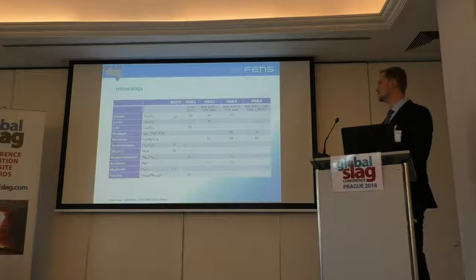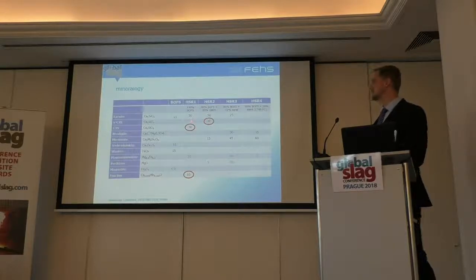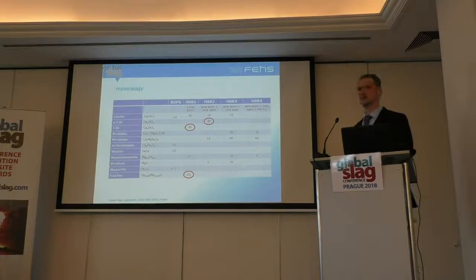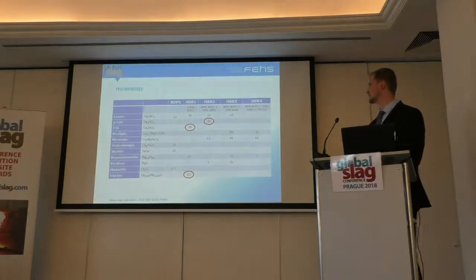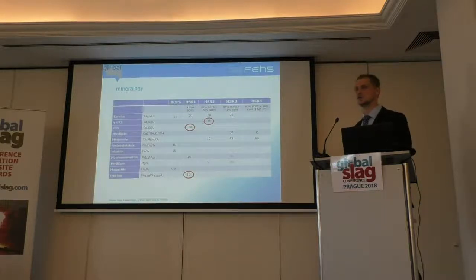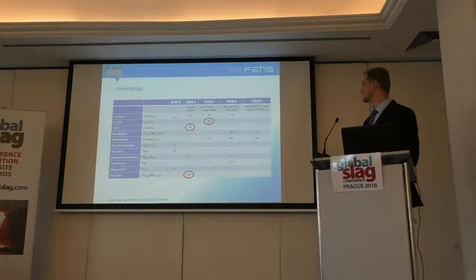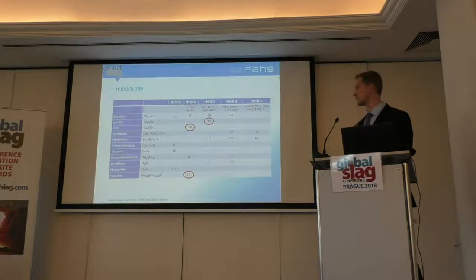When we are looking to the mineralogy, just very fast, the reference slag that was reduced by carbon without any treatment, we had about 30% tricalcium silicate, so very good for the cement industry, but also 10% free lime. But this slag was not able to be handled in a bigger scale. Where we added some blast furnace slag, we got gamma dicalcium silicate, typical for secondary metallurgical slags, so it's disintegrating. And when we are looking here to the fourth trial, where we increase the temperature, it was able to handle the slag, but no tricalcium or dicalcium silicate, so it's not really useful in the cement industry.